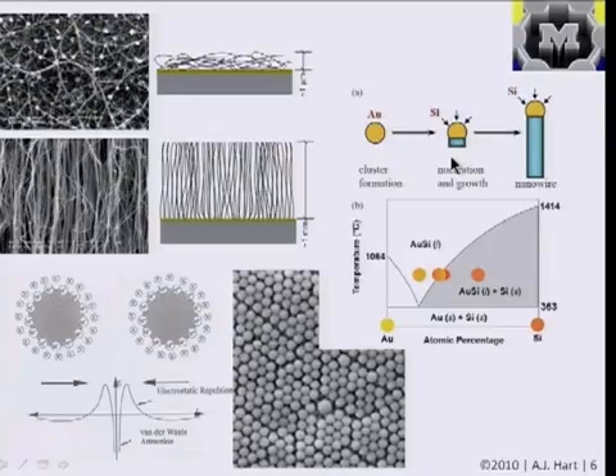For example, why silicon nanowires can be grown at temperatures below the bulk melting temperature of gold. Incidentally, when you make silicon nanowires, you have gold and silicon present, and silicon from the gas phase dissolves into the gold, and then you form a gold-silicon eutectic. But the location of this eutectic point at the nanoscale is lower than it would be if you had a